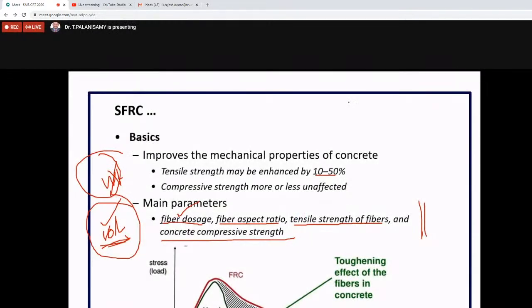So that's why most fiber is taken by volume. That is called the volume fraction. For example, for 1 meter cube of concrete, how much volume of fiber you want to add or replace, whatever it may be, that is called the volume fraction. This may be 0.25, 0.5, 0.75, up to not more than 2%. Okay, so that is called the fiber dosage. So we want to control the fiber dosage and fiber aspect ratio.